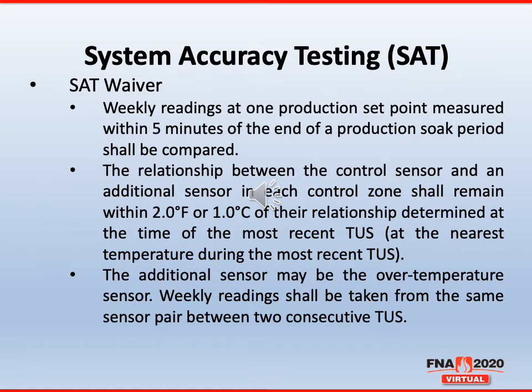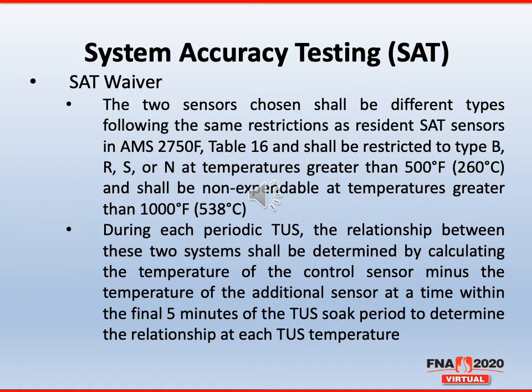The additional sensor may be the overtemp sensor. Those weekly readings shall be taken from the same sensor pair between 2 consecutive TUSs. Lastly, along with the waivers, the 2 sensors chosen shall be different types following the same restrictions as the resident SAT sensors in AMS 2750 Table 16, and shall be restricted to types B, R, S, or N at temperatures greater than 500 and shall be non-expendable at temperatures greater than 1000 degrees Fahrenheit.